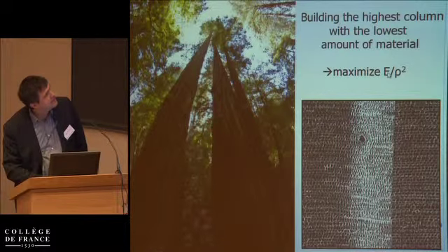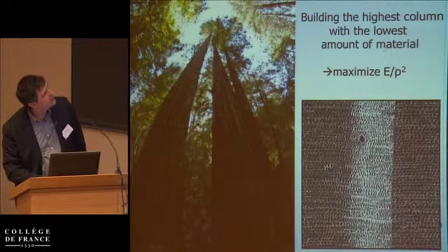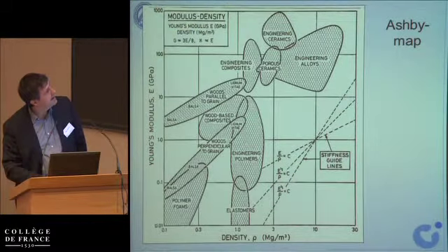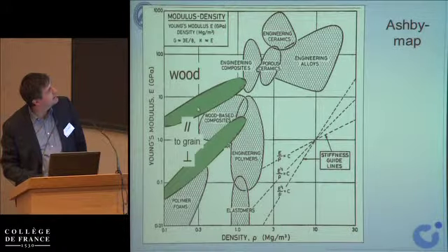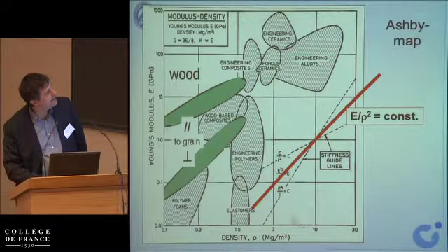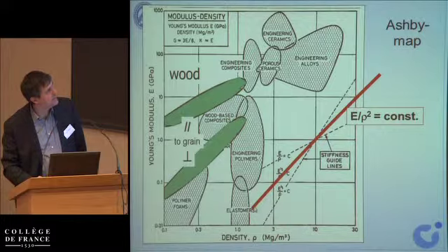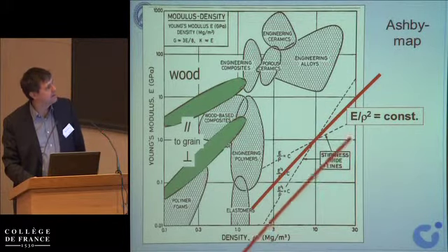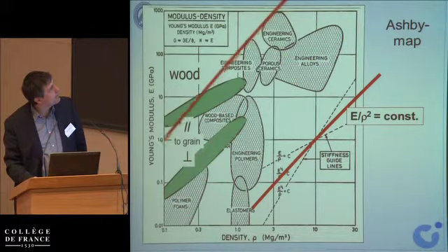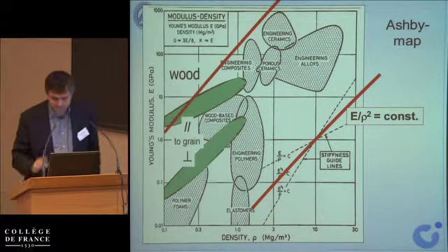So if you want to build the highest column with the lowest amount of material, this is what you need to maximize. And here is an Ashby map actually collected, I think, by Mike Ashby in a very early paper already, with all kinds of materials, engineering alloys. And here is wood in the direction of the fiber. Well, perpendicular to the fiber is not important because it's not used that way in nature. And now this is a log scale, and this is the line that has constant values of the parameters that I'm interested in. I'm now increasing this interesting parameter. And you see that well, wood is better than anything, at least for this parameter.